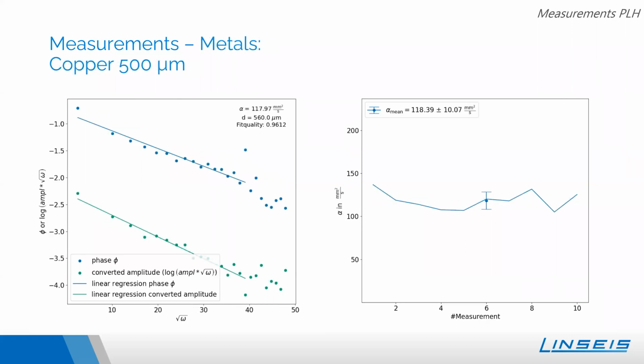Last but not least, here's an example of a really, really thin sample of copper, a metal with a high thermal diffusivity of 117 millimeters square per second. Moreover, our instrument could even handle this difficult sample and extract the correct value of the thermal diffusivity of the copper sample really well. And also the repetition is quite okay, I think, for such a thin sample.